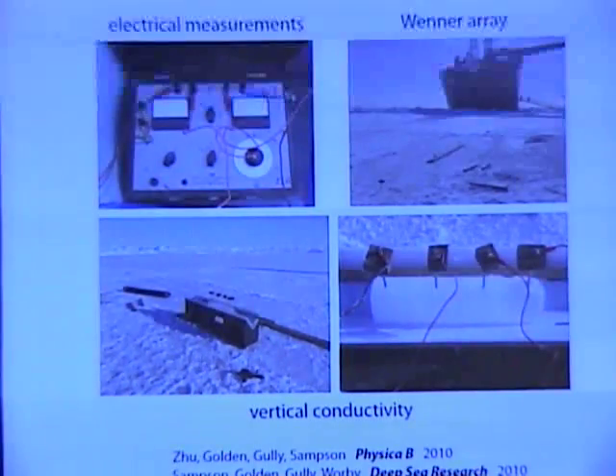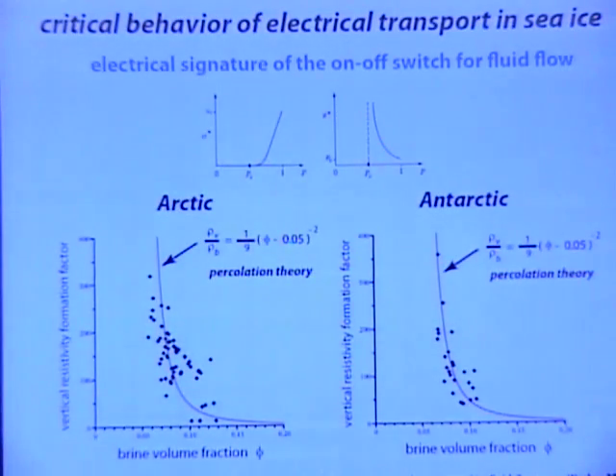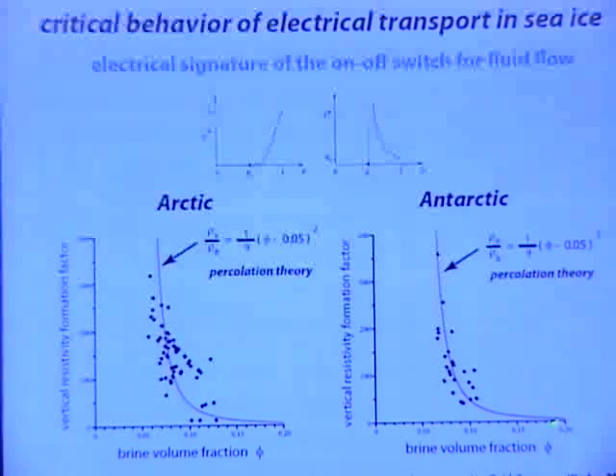We found, this is the big result here, from our direct measurements, we found the electrical signature of this on-off switch, my rule of fives, but for electrical conductivity. So that means there's a divergence of the resistivity, 1 over the conductivity, as you approach 5%. This is our Antarctic data. I then looked at my colleagues' Arctic data from a completely different method, and we see the same behavior.